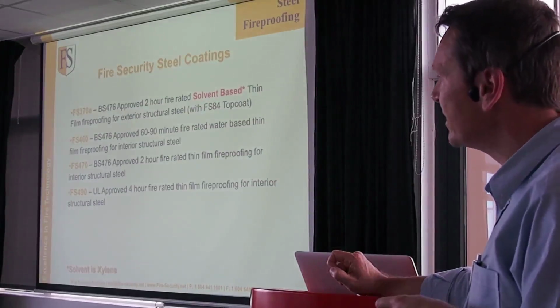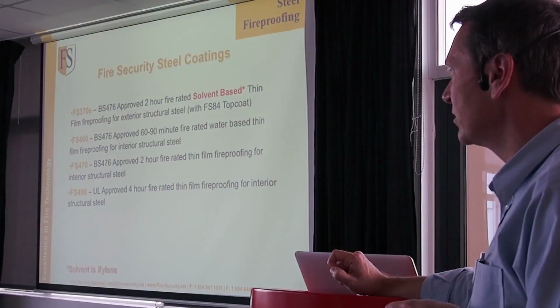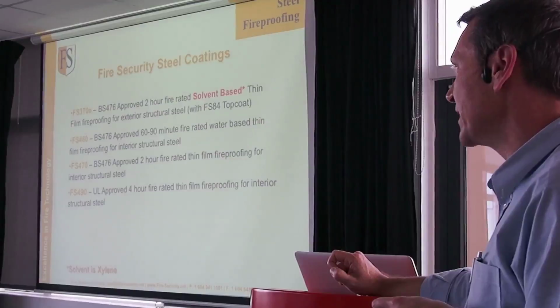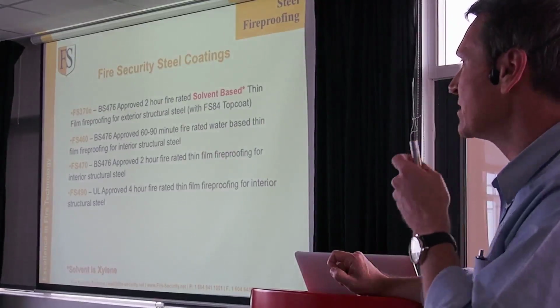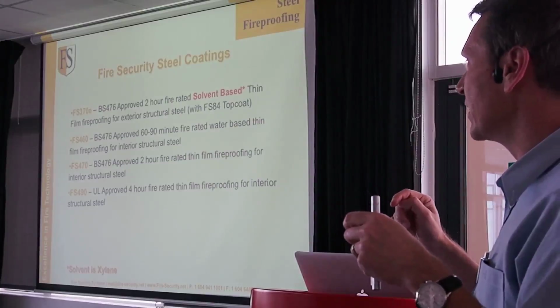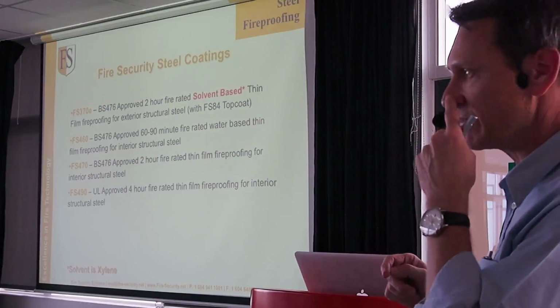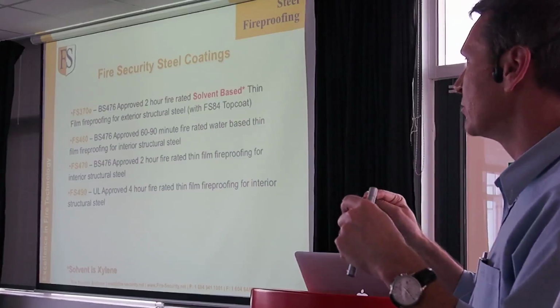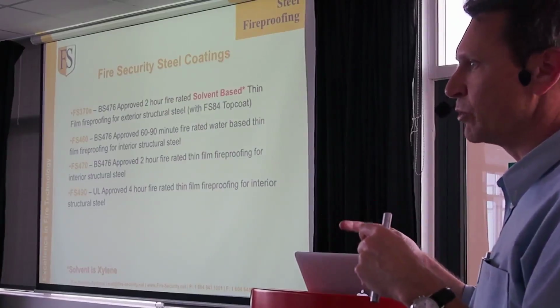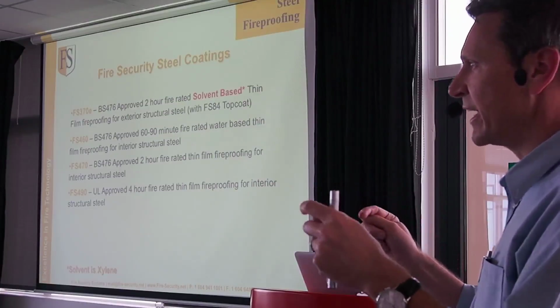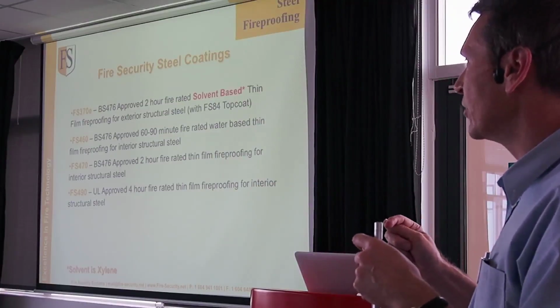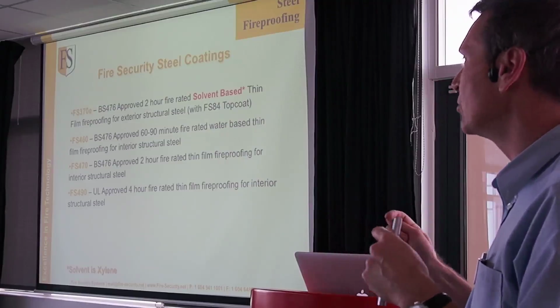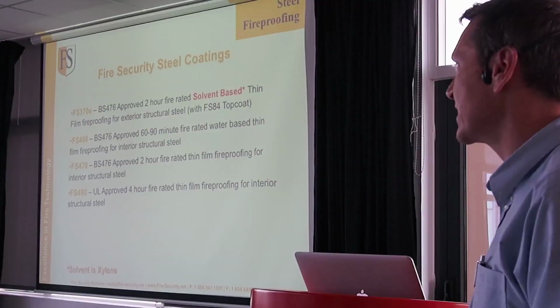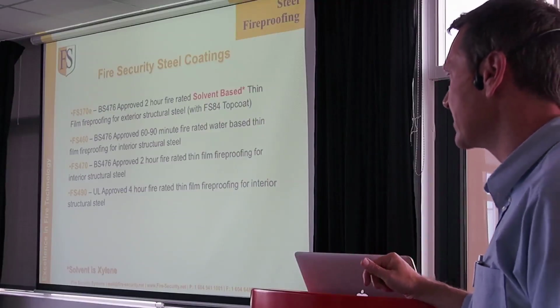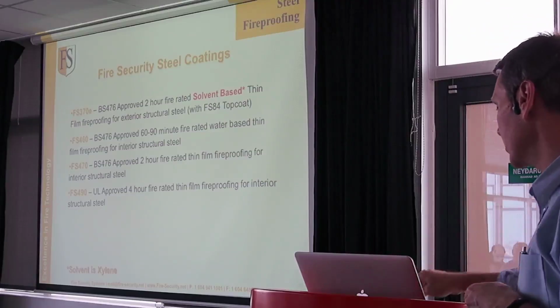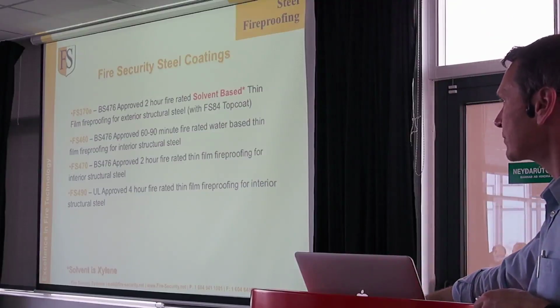And the main reason why we have a difference is there's a different test method for UL to British standard. The main difference is what's called flux in furnace, and that means that in the furnace, in test of a steel section, even fire stopping for that matter, they inject airflow to show what a real world application would be like. But it's a set airflow under British standards. Under UL, it's not set. It happens all the time in all different ports and at 360 degrees on the section. So it's actually a harder test to get by. But we have it, so there's a multitude of applications for it.